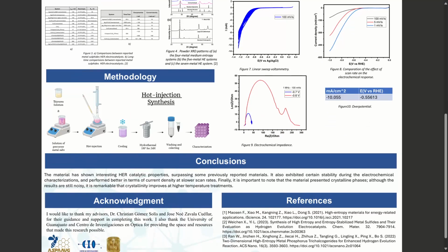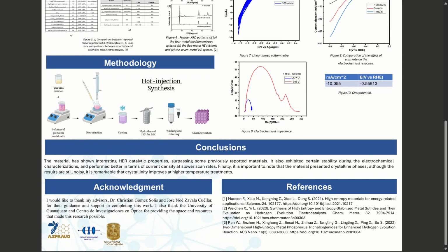To put this into context, platinum still remains the best performing catalyst for HER. However, its cost and scarcity make it impractical for widespread hydrogen production. Among transition metal sulfides, many reported systems show moderate activity but often lack stability. Our high-entropy sulfide catalysts outperform several of these reported systems, both in terms of overpotential and in stability.